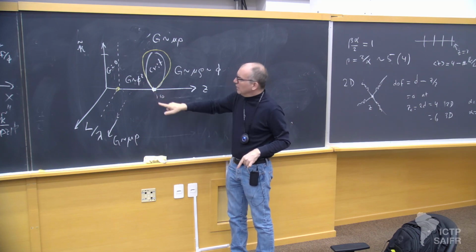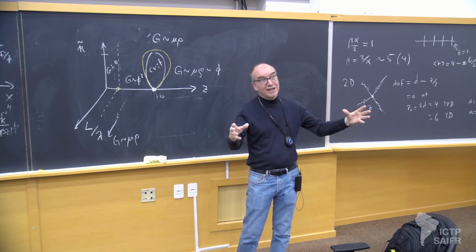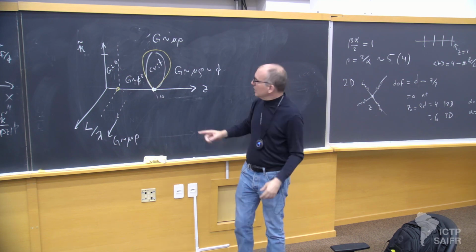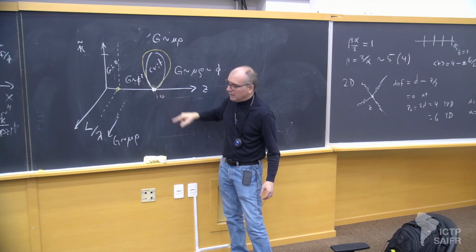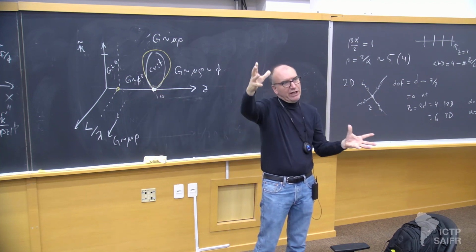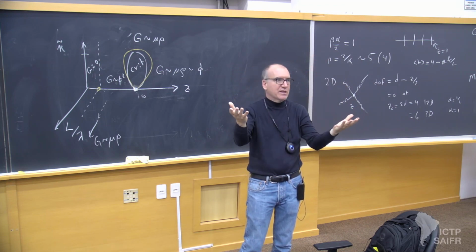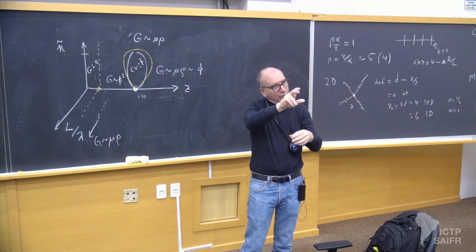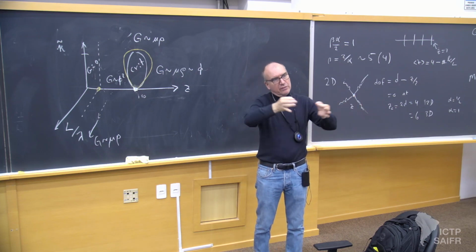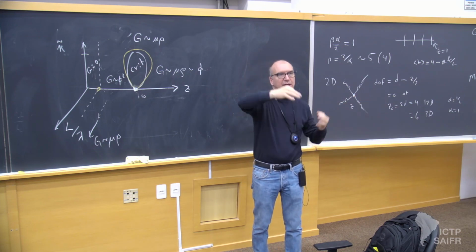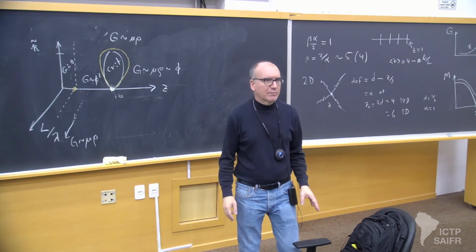But what I wanted to also mention is what's more subtle is the range of correlated fluctuations grows. There's a correlation length which grows. So what you should imagine is when I get near this point, even at finite kappa, so somewhere down in here, as I move through this region, I'm finding massive regions of the network undergoing significant deformations. That's also a bit different from what Andrew was just telling us about, local rearrangements, for instance, in a glass, right? It's partly because of this network, this architecture with potentially long fibers that you get some long-range effects, which are different from jamming. Of course, in jamming, you also get a divergent correlation length. But